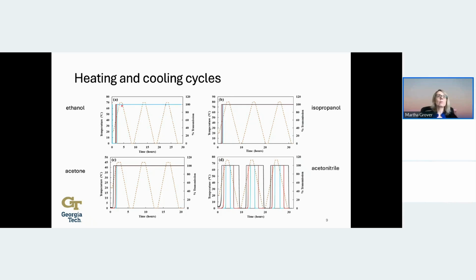Now, we know that we're supersaturated because we're below the solubility once we move below this blue line. But somehow there's not enough driving force, not enough time in order to actually nucleate crystals. So it's more of a kinetic phenomenon. If we look at the isopropanol, we see something very similar. We initially are able to fully dissolve the crystal, but then we see no crystallization. Also true for acetone. We also do not see crystallization, but we do see crystallization for the acetonitrile.